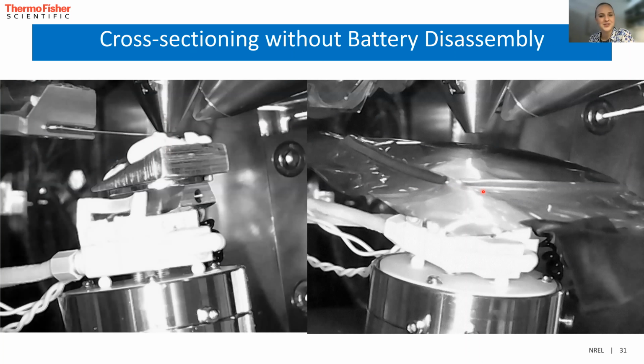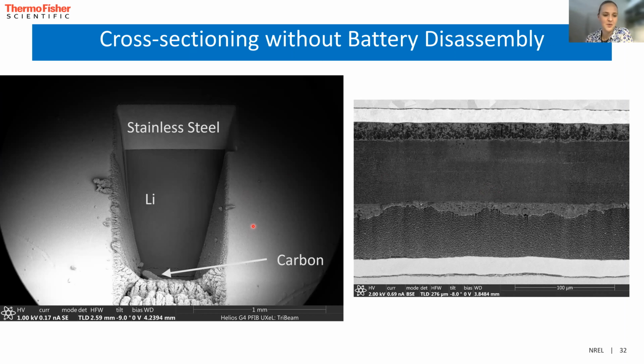We also learned that we didn't want the counter electrode on the top side of the coin cell, because we started out with a 750 micron lithium counter electrode, and that was a bit too thick. This is imaging all the way a millimeter down, and then at the very bottom you could see the battery stack. So what we did was invert everything and go to a thinner counter electrode for the lithium metal. Instead, this is a 50 micron lithium counter electrode.